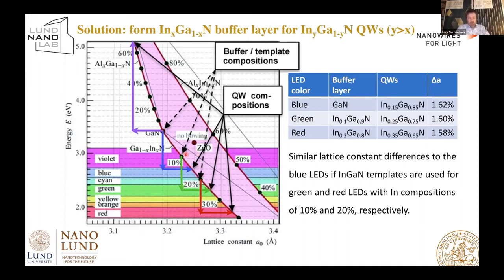And you continue to see if we can, still it was a proposal, if we could put 20% indium into the plane of substrate we're growing on, then we would, with exactly the same exercise, get to 35% indium in efficient red emitting quantum wells. So this is summarized also in the little table up here.